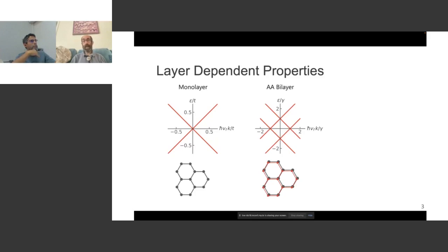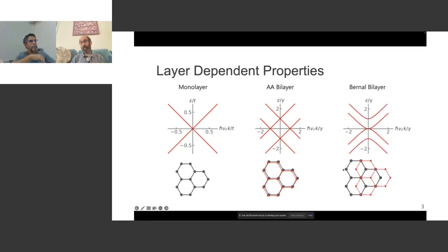In fact, in natural graphite, the way that layers sit are so-called Bernal stacking or AB stacking, where if you have one layer, then the next layer will have half its atoms on top of atoms of the first layer and the other half of the atoms above the holes in the hexagons in the layer below. And you can see there's a dramatically different expected energy versus momentum. In fact, it may look kind of quadratic. It's a little more complicated than that. But I just wanted to give you the sense that the details of stacking matter a lot.